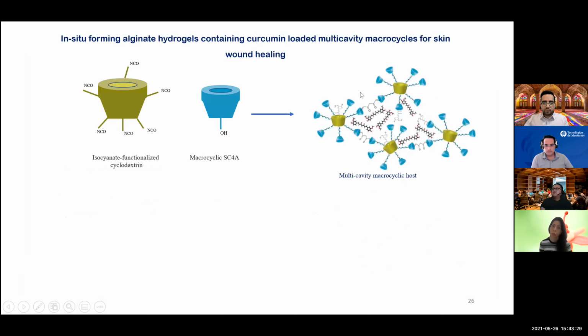For that reason, we did another project, and we are still working on it because we have only done the first step, and accordingly we used isocyanate functionalized cyclodextrin. We functionalized the surface of this cyclodextrin with isocyanate, and after that we add another host, sulfonated calixarene, which is the usual host that we can use for these techniques. And accordingly, through the interaction between hydroxyl group and isocyanate group, we have some urethane linkage, and we produce a multi-cavity host for these applications. And after that, we loaded these multi-cavity hosts inside of the alginate gels and produced some wound dressing again for different applications, for example, for skin wound healing.